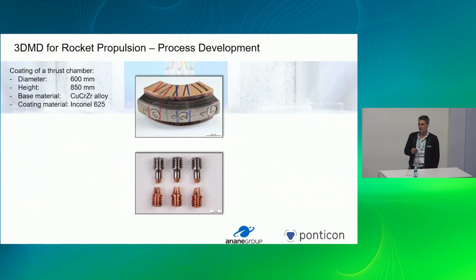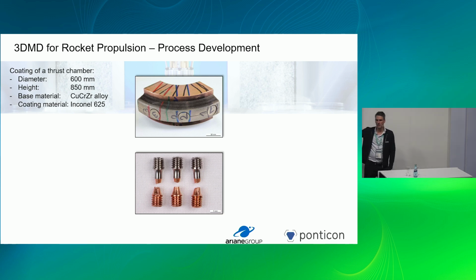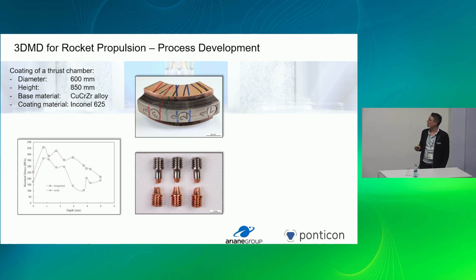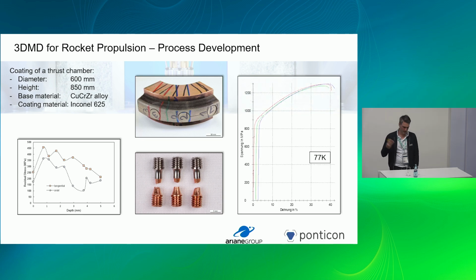I just mentioned those tensile specimens. I don't want to spend too much time on it, but just to give you an impression, it fails how it's supposed to fail inside the copper section, which means the interface is sound and has all the required properties, and the material we applied itself is the way it's supposed to be. We did some measurements on the stresses on the inside, both in tangential and axial direction. What you see is there's a decline the further we get in, which is also a good sign. And then again, the purpose of this is to fly it to space. So it's also interesting to see how the materials perform in those ambient conditions. So this is tensile testing at cryogenic temperatures.